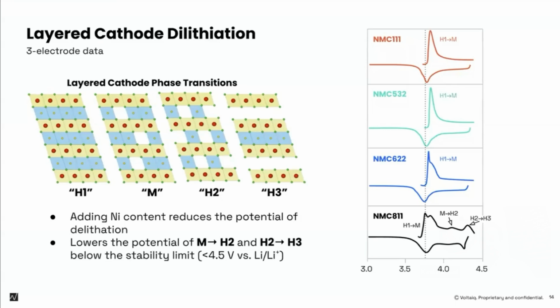As we go to higher and higher nickel contents, it basically brings the access to those voltage transitions down into lower voltages. Now for the same amount of voltage, going out to I think this is 4.4 or 4.35 volts here, you can start to see that we're able to access more of the lithium from within this structure. That's the big benefit of going towards nickel. And you can clearly see that in DQDV, because DQDV is helping you understand and see the thermodynamics of the reactions that are taking place here.